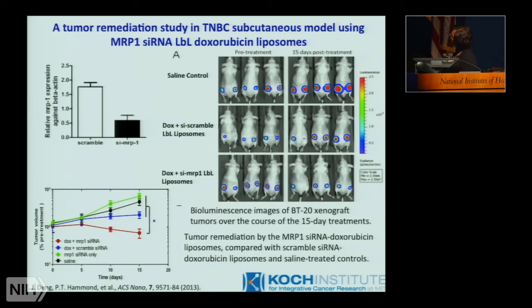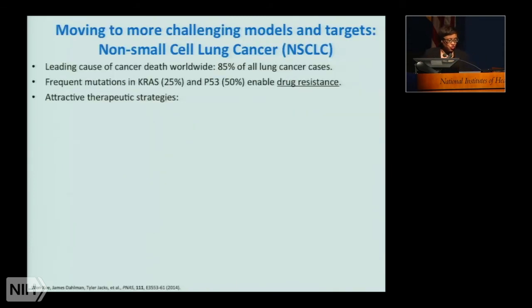When we examined tumor remediation in these animals using a xenograft model, we find that in the saline control, we're getting, of course, this rapid growth of the triple-negative breast cancer. If we look at doxorubicin with the scrambled siRNA, we see that we are reducing the growth of these tumors, but not their size. They're still essentially doubling in size. However, if we treat these with the combination system, we do see that the tumor size is getting smaller, and we're getting some real regression. So we're very excited about these results, and we began to move to a more challenging model.